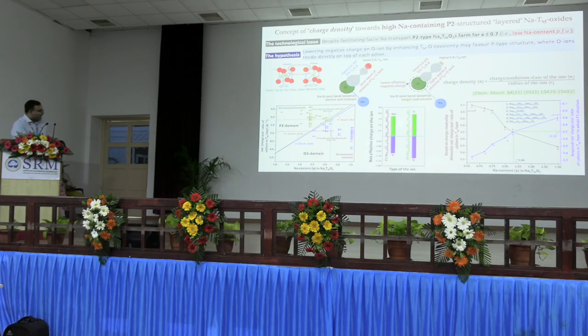In addition to that, a greater covalency of my transition metal oxygen slab also lowers the effective positive charge on my transition metal ion, and that is important because in a prismatic coordination there will be face sharing between the transition metal ion and the sodium ion. So if my transition metal ion is less positive in terms of effective charge, the repulsion between my transition metal ion and the face sharing sodium ion will also be lower. So overall, if I increase the covalency of the transition metal oxygen slab, I can have more stable P2 structures, even with more and more sodium content, which will bring these two closer.